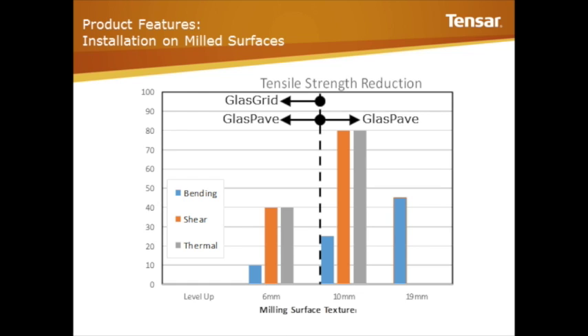Now, I'm not going to go into this in depth because it's quite expensive, but if you just take the bending type of distress, then what we're saying here is at 6 millimeters, you have, roughly speaking, a 10% loss of strength if the material is installed directly on that grind. So what we do recognize is that there is some loss of serviceability associated with putting it directly on a ground surface, and that stands to reason because it's a stiff product, and you are going to get some installation damage. And remember that we account or allow for almost 30% damage associated with installation anyway, so you could eat that up pretty comfortably with respect to using it on a micro mill of 6 millimeters.